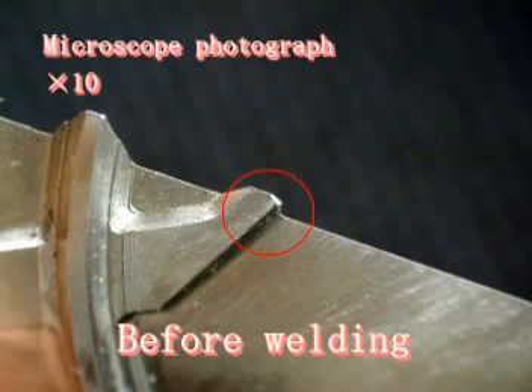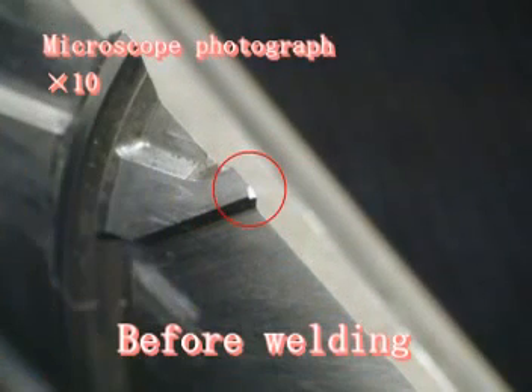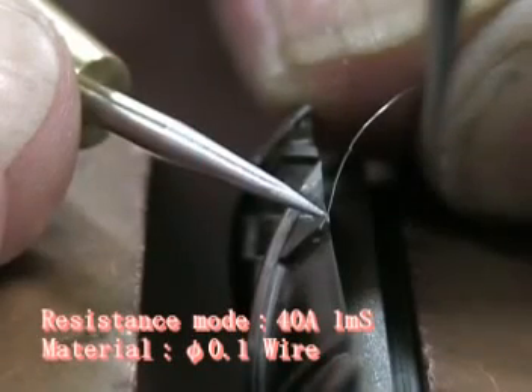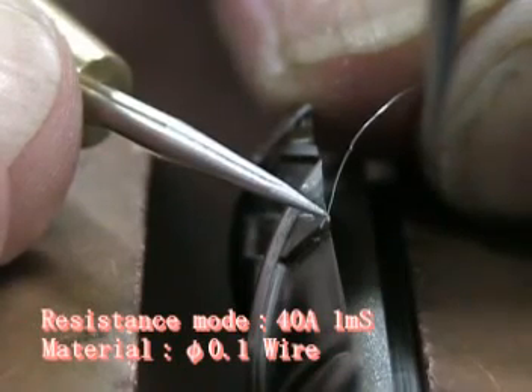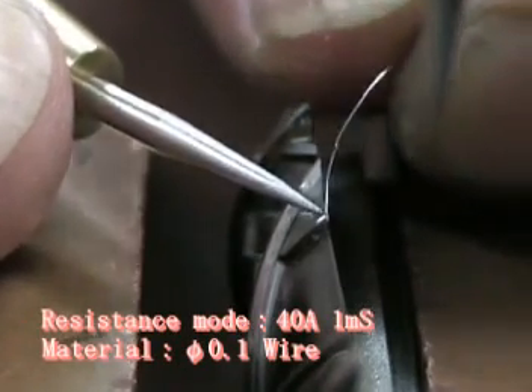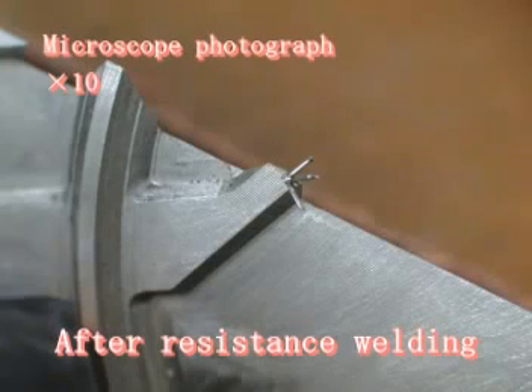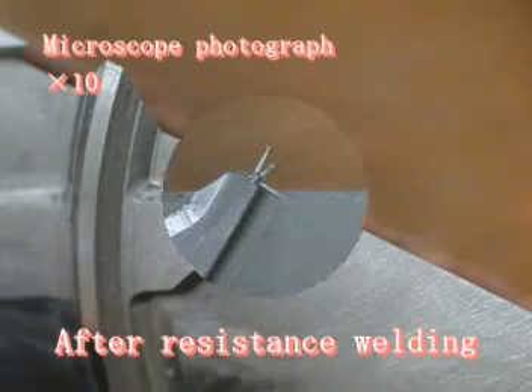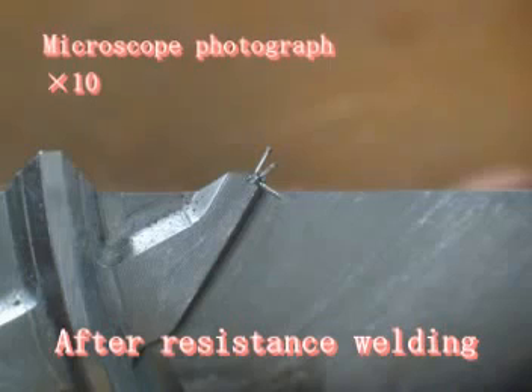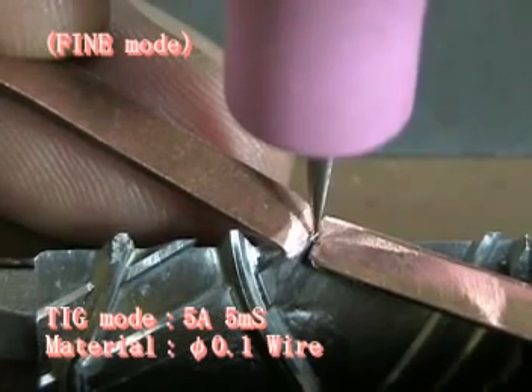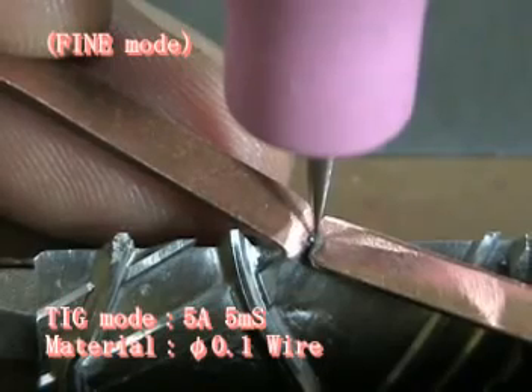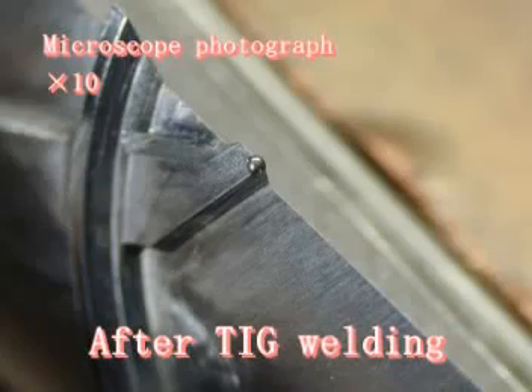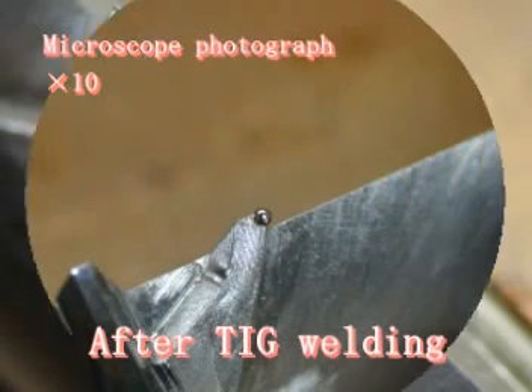This is a shot using a 10x microscope. 0.1 wires are used for this purpose. Fix 3 wires extended from the target points in this way. Apply copper plates on both sides to avoid shrinkage and weld the 3 wires together. You can see all 3 wires are melted and welded firmly.